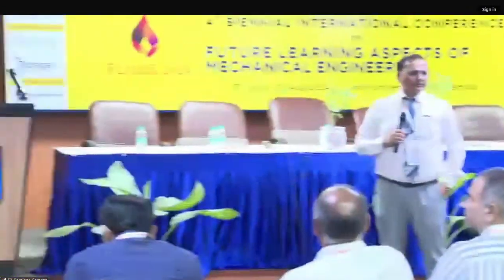Thank you, sir, for the wonderful presentation and for highlighting how we can functionalize the material and use it for different properties. My question is, does the titania size matter, since it depends on photocatalysis? You have shown it in the nanometer range. If we increase the size, does it affect the photocatalysis rate? Yeah, typically we try to use material somewhere around the 20-40 nanometer range. And if we alter the size, we found that it changes the photocatalytic degradation rate. But mostly, when you go down in size, it's much better.